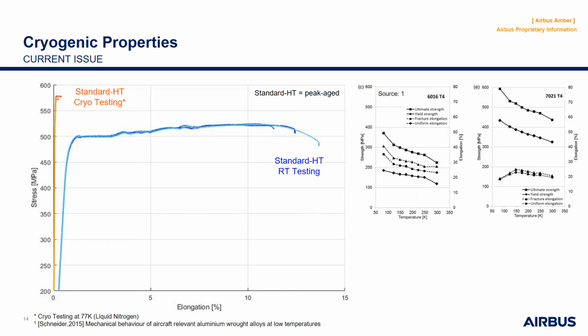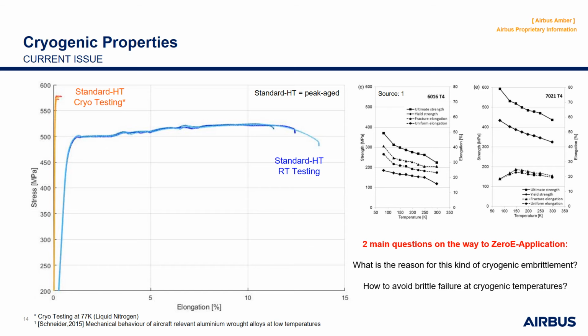Testing Scalmalloy in our current heat treatment state, which is peak aged, at 77 Kelvin, a different behavior can be observed. The elongation was reduced down to less than 2%, which is an embrittlement of our alloy and by far not typical for aluminum alloys, which leaves us with two main questions on the way to our zero-E application. What is the reason for this cryogenic embrittlement and the fundamental mechanisms behind the phenomenon? And how can we avoid this brittle failure and prepare the ground for additive manufacturing applications in the future?